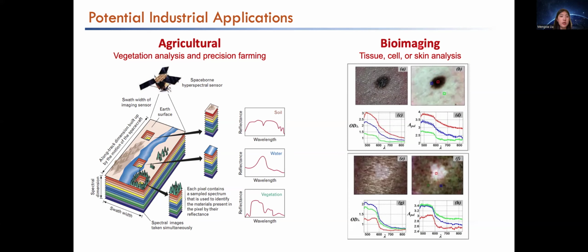And furthermore is bioimaging, because cells, tissues, or skin can reflect light with different responses under different colors and different polarization states. So here are some examples of skin components reflecting light under different polarizations and different colors. And we can see that for different places of the skin, we can get very different responses from the different colors and different polarizations. So if we can fully open the dimensionality space to use and detect light with full information, we are able to get more detailed analysis for biomedical diagnosis.